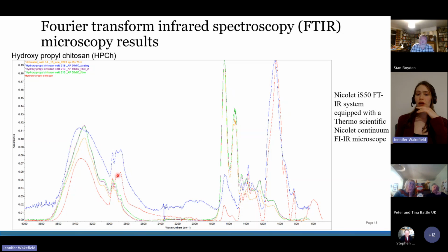So with this blue one, that is where you can see that the coating was visible on the polymer, and you can see it matches with the polymer. So this peak there is not present in the untreated wool, but is once it's treated. So, and it matches the polymer. So this is only possible because the infrared microscopy that we have also has a microscope attachment. So we're able to look specifically at the coating, because otherwise there was such a strong signal from the wool that we're struggling to be able to identify the consolidant. But with the microscope as well, where we can narrow down exactly where to look, where we can see there's some consolidant on the surface, that allows for the identification of the polymer.